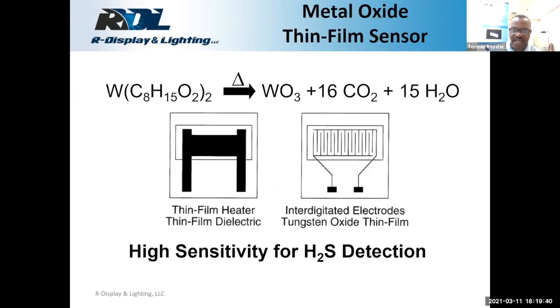This is just a slide I threw in to complete a little summary of the type of activities that I had at Eastman Kodak working on electronic materials. Here we're showing the use of tungsten carboxylate precursor materials to form thin films of tungsten oxide deposited over interdigitated electrodes. We carried out this chemistry to fabricate high sensitivity hydrogen sulfide sensors.